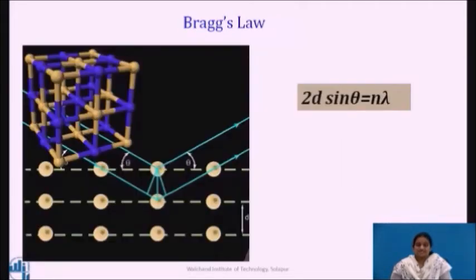When an x-ray beam is incident on the crystal, each atom in the crystal scatters a portion of the incident beam. The scattered waves travel in all directions. Now, the question is, do we have to consider all these scatterings for crystal structure determination? So, the answer is no. It is convenient to consider the net scatterings by atoms in terms of the diffraction by the crystal planes. Each family of planes give rise to scattering, but only certain family scatters constructively in certain direction.